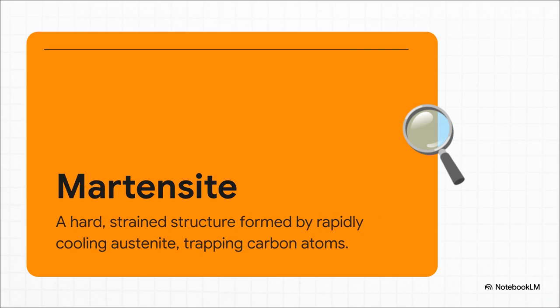And this is what we're aiming for, martensite. Once our austenite sponge is full of carbon, we cool it down, and I mean fast. We quench it. This rapid cooling essentially flash freezes the atomic structure into this new form, martensite. All those carbon atoms get trapped inside, twisting and distorting the atomic lattice. This creates a ton of internal stress, and that stress is where the incredible hardness comes from.